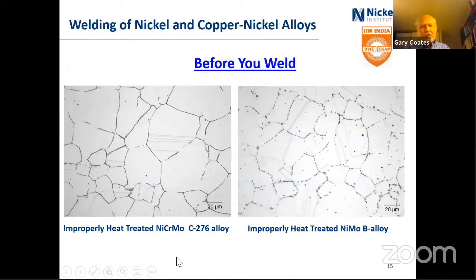And some of us like micrographs with bad phases that are in there. And I'll just show you a picture of C276 and B alloy that have been badly heat treated and have lots of grain boundary precipitates. It's not carbides there. There may be some carbides there, but there are other phases. They're mu phase for the C alloy and a nickel molybdenum phase for the B alloy.